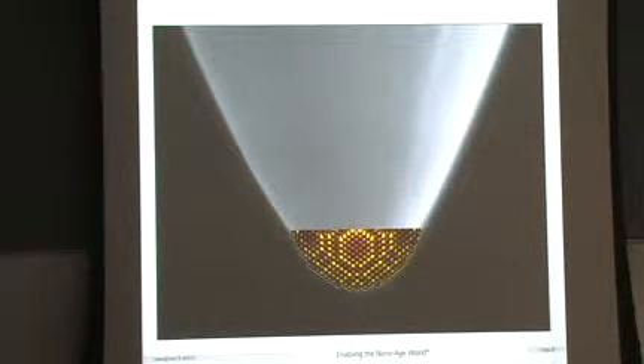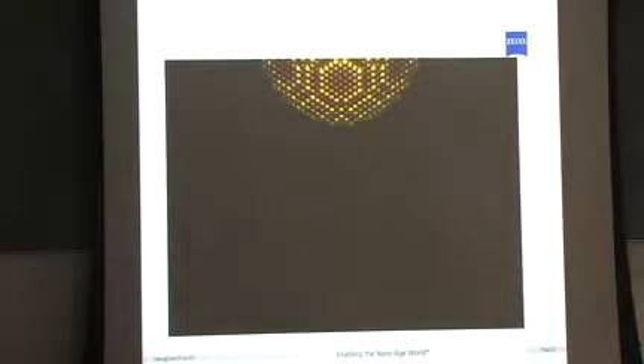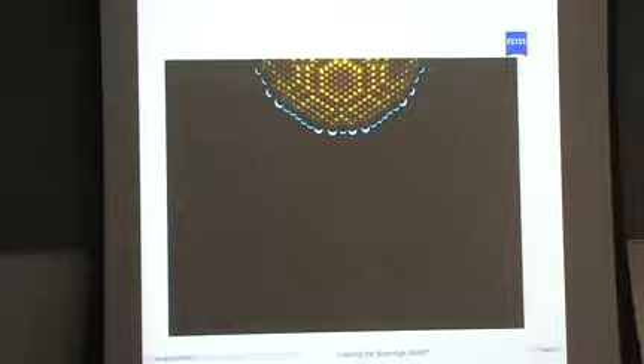So if I put a voltage on this, let's say 20 kV positive, the interesting thing that happens is there'll be regions where I get electric fields as large as 3 or 4 volts per angstrom. That's about as big an electric field as you can get anywhere near matter. Beyond that, you actually start to rip the atoms off one by one. But just shy of that, that electric field in these little moon-shaped areas, what we call the ionization disks, is so big that if a helium neutral atom wanders into these disks, the electron will quantum mechanically tunnel out and go into the metallic crystal of the emitter. And the remaining ion, positively charged, sees the 30 keV on the bulk emitter and accelerates away.